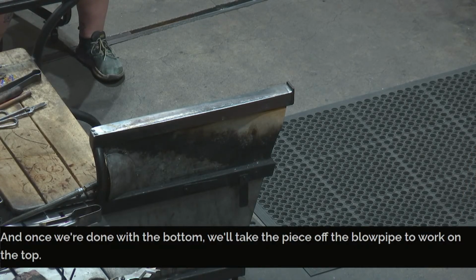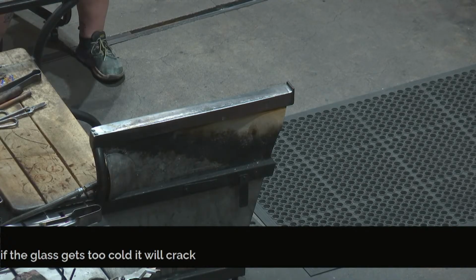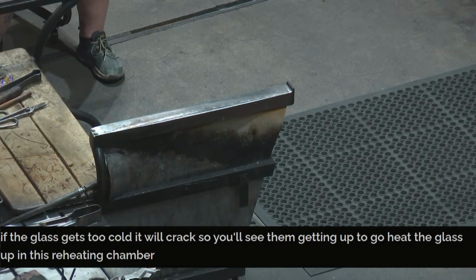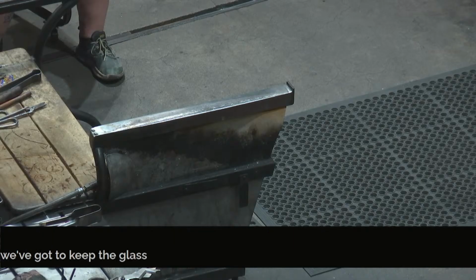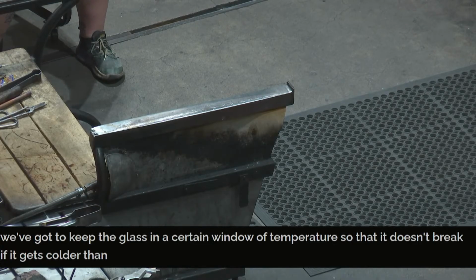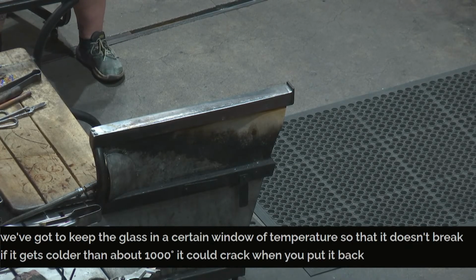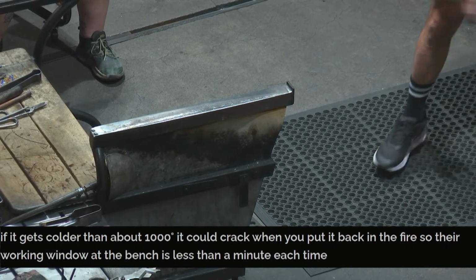If the glass gets too cold, it will crack. So you'll see them getting up to go heat the glass up in this reheating chamber. We've got to keep the glass in a certain window of temperature so that it doesn't break. If it gets colder than about 1,000 degrees, it could crack when you put it back in the fire. So their working window at the bench is less than a minute each time Gabe sits down.